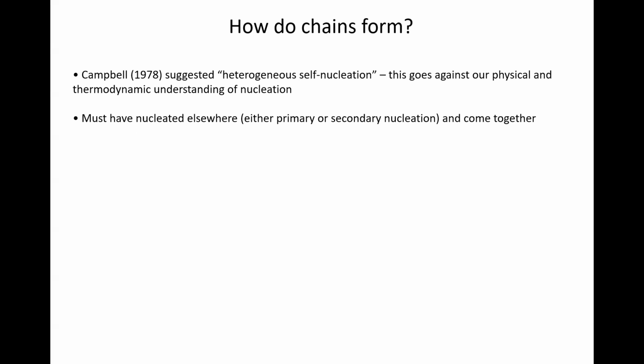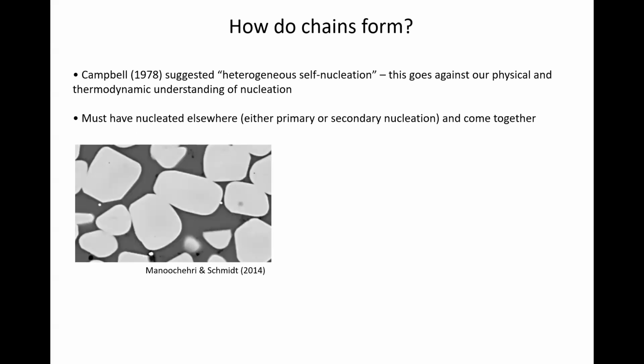Now, the easy way of understanding that, which was the primary explanation for secondary nucleation, is when you've got an industrial crystallizer and you're stirring it, and the phase you want is forming dendrites, and the stirring breaks off tiny little crystals or seed particles from those dendrites, which then act as the nucleus, if you like, of other grains. That's what secondary nucleation is. Right, so why would they come together if they were nucleated elsewhere?